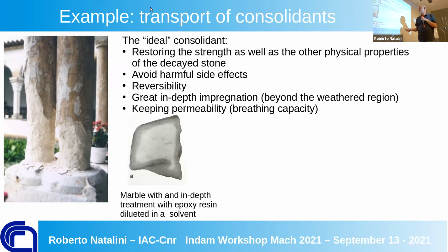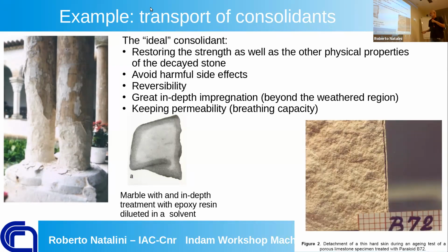But it's not easy. Here, for instance, is a marble with an in-depth treatment with epoxy resin. And you see that it's very difficult to have an effective penetration of this kind of material. And sometimes you have even some drawback, in the sense that here you have detachment of the external layer, because the mechanical properties of the external layer are different from the inside properties. So after consolidation, you have even worse, you have exfoliation and so on.